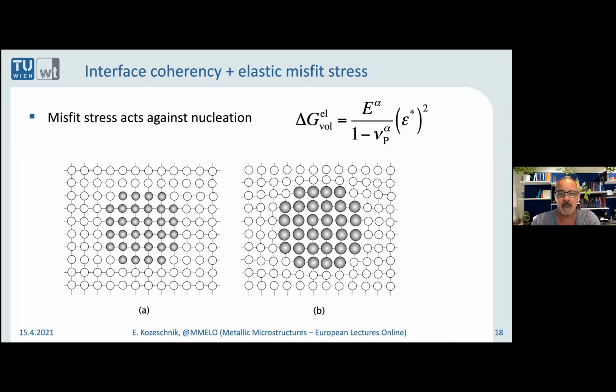The precipitate is the dark balls. And on the right side, I have plotted the case where the precipitate contains atoms that are larger in volume compared to the surrounding matrix. And in that case, and that is very typical for solid state precipitation or nucleation reactions, we have some elastic energy. The stress field always acts against the nucleation process.